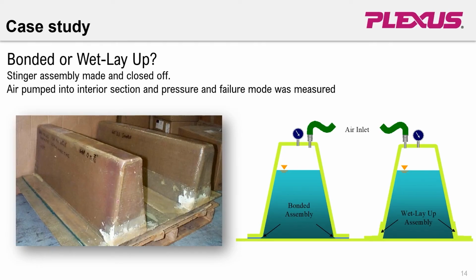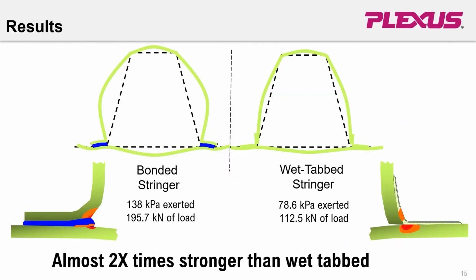If you still have a customer that's still doing a wet layup process and is curious about the strength of Plexus versus a wet layup, we've done numerous tests where we'll do a bonded stringer section versus a wet layup stringer section, and we'll actually pump in air to create a high pressure vessel almost to see when it fails. So in this instance, because Plexus distributes stress so well, it has really good balance of properties, not only strength, but peel resistance. The amount of pressure or force that it could hold is almost twice as much as the wet tab system, because that's a concentrated stress area. So this is a huge advantage for long-term durability of these marine vessels.